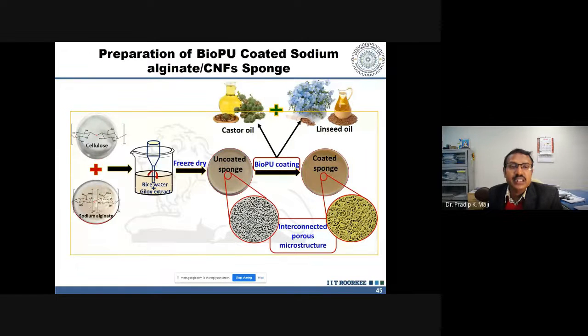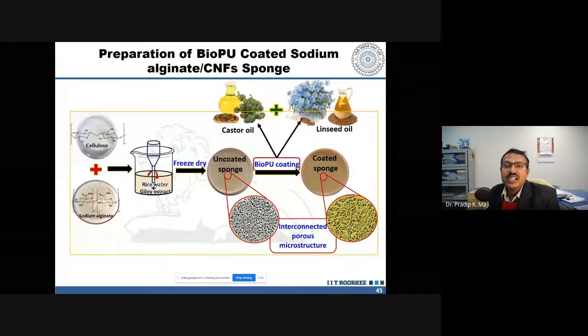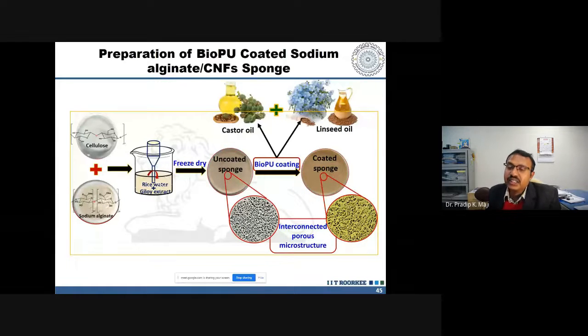So what can we do? Definitely we can do something. Here we have reported that biopolyurethane coating on sodium alginate CNF sponge can be utilized, where mechanical stability in the wet environment can be retained, so that for long durations it is not required to change. We have developed castor oil based or linseed oil based biopolyurethane coating material that has been coated onto the cellulose sponge, and that cellulose sponge has been used for wound dressing application.